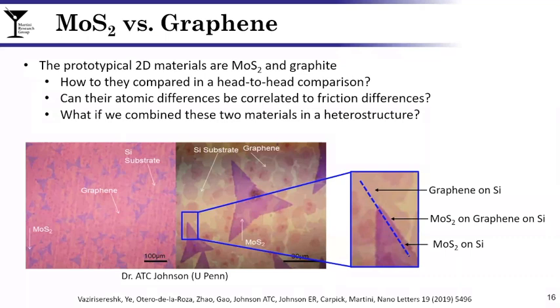The reason this is a very powerful and exciting sample for us is that if you look at the image on the right, the close-up view, you can see that along that scan line drawn by the blue line, you can slide with the AFM tip along one direction and cover MoS2 on silicon, MoS2 on graphene, and graphene on silicon. So we can really do a head-to-head comparison between graphene, MoS2, and them together, which I'm calling here a heterostructure.